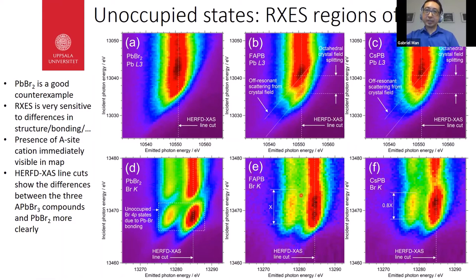In addition, we also noticed that the width of the main edge is different between formamidinium lead bromide in figure E and cesium lead bromide in figure F, where the width is roughly 80% for cesium lead bromide. So this is very promising. It shows that resonant X-ray emission spectroscopy is very sensitive to differences in the structure and also in the bonding of these compounds.